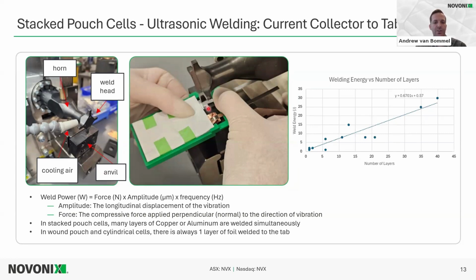So the weld energy and the weld power needs to be selected such that that gives a good weld. So the weld power is a function of the force applied, which is that compressive force normal to the amount of vibration, the amplitude, which is the displacement of that vibration, and the frequency of vibration. So again, in those stacked pouch cells, many layers of copper or aluminum are welded simultaneously, and it's also welded to the tab. So nickel in the case of the copper or the anode tab, and aluminum in the case of the cathode tab.